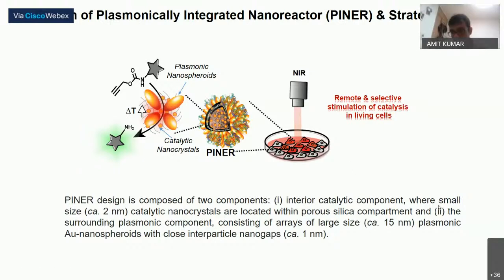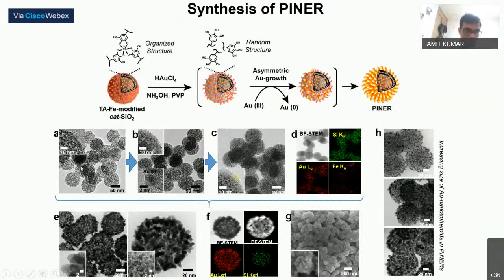Using our knowledge of chemistry and some already established methodologies, we started synthesizing this design of the nanocatalyst. We started with mesoporous silica nanoparticles. In TEM images you may not see the pores very clearly, but the structure of such nanoparticles is like a sponge which has 2 to 3 nanometer pores. By simply reducing the metal salt right in this, you can functionalize very small nanocrystals into these mesopores. Some of the nanoparticles are also modified on top of these silica nanospheres. So now the catalytic component of the nanoreactor is ready.